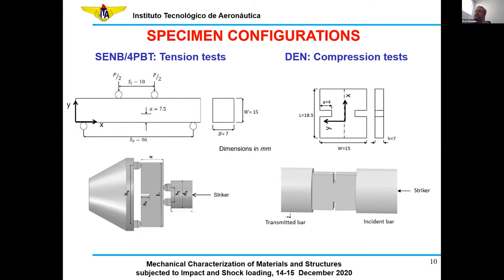Some of these setups or specimen configurations are shown here in this slide, where one of them is the four-point bending test, where we have a translaminar crack going through the thickness. You're talking here about intralaminar fracture toughness. We use this specimen configuration for measuring the tensile fracture toughness associated with fiber breakage and matrix cracking. And on the right-hand side, we have the double edge notched specimen that we use to measure the fracture toughness associated particularly with fiber kinking, which is one of the failure modes that we have incorporated in our damage mechanics-based model. All these specimens were designed in a way that we have a very high stress concentration at the crack tip or in the notch, which is a desirable feature.